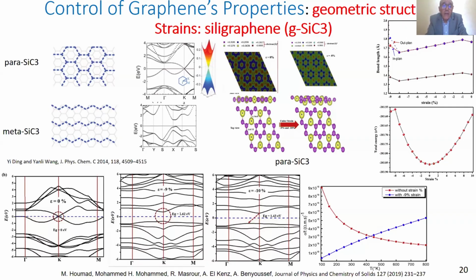for 9% of compressive strain, but higher than that, for 10, it's still semiconductor, but it is now an indirect band gap. So as you see, we can change the property of this 2D material by changing the geometry or by making some strain, that compressive or tensile strain can change the behavior. And as is shown by the electrical conductivity for the semi-metal, there is a decrease of electrical conductivity with temperature, while with strain it increases, which shows that it is a semiconductor.